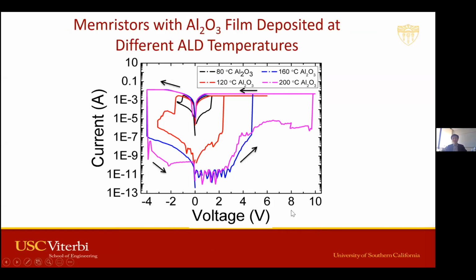Now we use the aluminum oxide deposited at different temperatures to build a memristor device. Here we built exactly the same memristor device, and for this device, the aluminum oxide layer thickness was 8 nanometers. This was the first IV scan of those 4 different devices. When you have a memristor device, you can do a so-called forming step after building it: you scan it, switching it on and off a few times. Depending on how hard you switch it on or off, you can have different IV curves for the later scans. But this is the first scan.